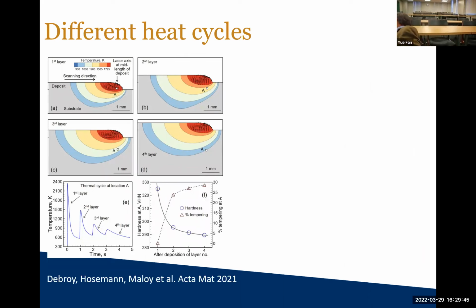Professor Debroy from Penn State actually did a beautiful modeling where he let the laser beam go across, calculated the temperature as a function of where the laser beam is, and then calculated the thermal history layer by layer. Remember, you do it layer by layer. So the next layer treats the layer underneath, and the next layer treats the two layers underneath, and so on and so forth. And they see different thermal history.